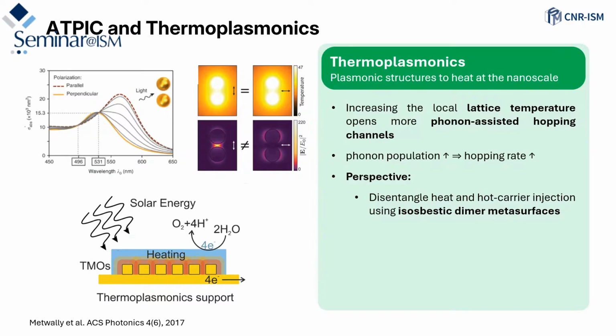The other part of the project, because of course, as I mentioned, we can modify the mobility just working with photons, but also with phonons. So the other part is using thermoplasmonics to enhance the mobility, just to heat up the transition metal oxide and also increment the hopping mechanism within the transition metal oxide. So of course, the first idea was to use this kind of isosbestic dimer metasurfaces, which should disentangle the heating part from the concentration of the light, which is also a phenomenon that can happen in this kind of system.